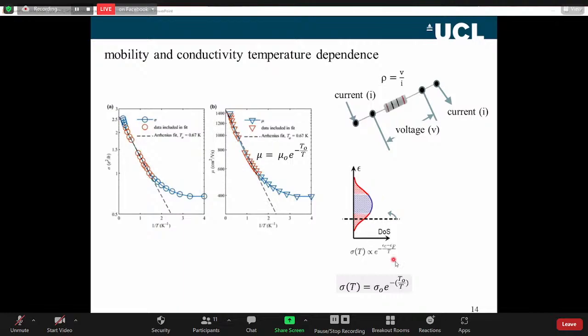It's an Arrhenius behavior. The temperature dependence of the conductivity is basically this energy here compared to kT, exp(−E_a/kT), or we sometimes just think of it in terms of a characteristic temperature, T_0. And so the conductivity was representative of transport to a mobility edge. We measured the mobility, and the mobility had the same temperature dependence, so it's the mobility that's activated, not the carrier density. If it was a doped semiconductor, you might say it's just activation of the carrier density, but it's not. It's actually affecting the mobility. They have the same characteristic temperature, fitting the conductance and fitting the mobility give the same temperature dependence.